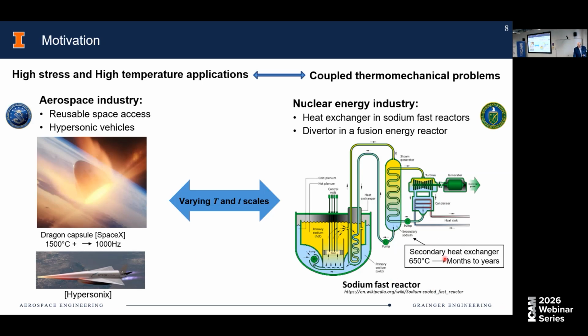Here, temperatures were on the order of 600-700 degrees C, but timescales were much, much longer. So the commonality in both these problems is that they essentially both have coupled thermomechanical effects, although the temperature scales and the time scales vary. However, we employ similar tools to study both, and I'm going to present results from both. As I said, I'm not going to dive deep into each one of these, but I'll show you how they connect with each other.